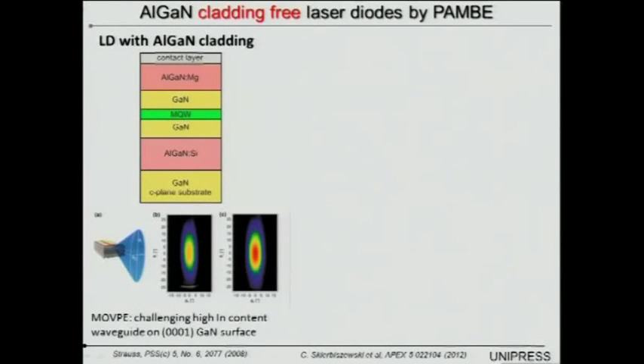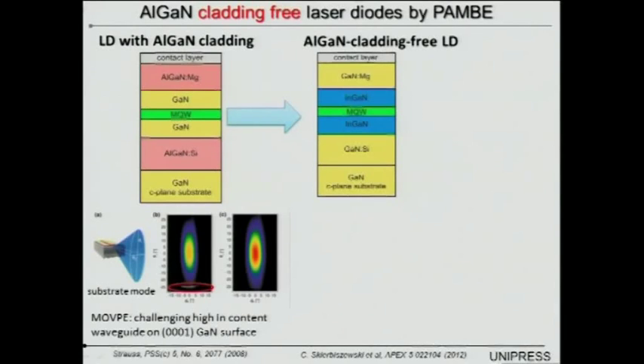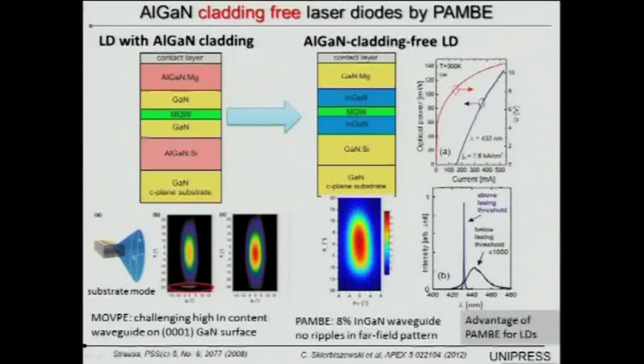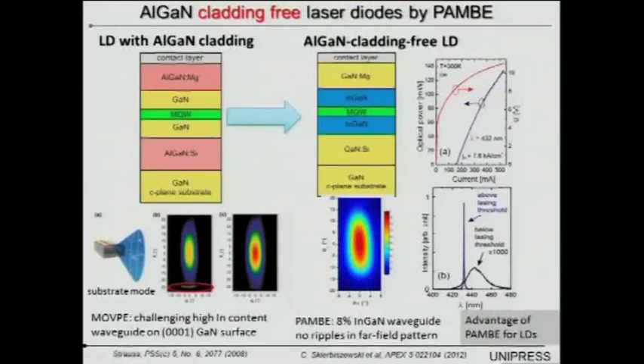Here, I just want to demonstrate the difference with aluminum gallium nitride cladding and then without the aluminum gallium nitride cladding. And here is the far field pattern with and then without. He finds that with this structure here, he has no ripple in the far field. And the lasing has an extremely outstanding low threshold at 430 nanometer wavelength.